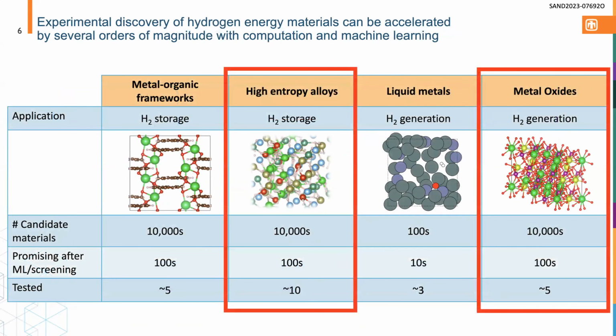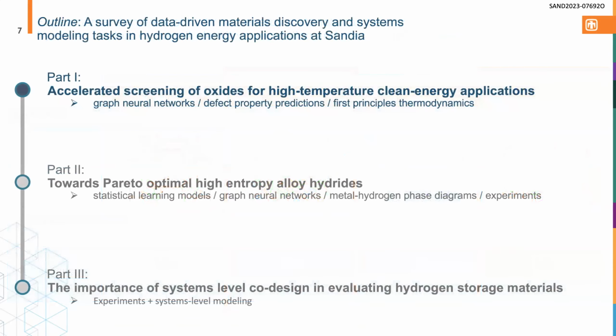So we look at a lot of materials at Sandia for hydrogen energy. Some of the things we touched on are metal organic frameworks, high entropy alloys, liquid metals, and metal oxides, kind of split between storage and generation there. The common theme is that there's tens of thousands of candidate materials, and we use machine learning to reduce the number of materials that are considered promising by several orders of magnitude, that basically shortlists things that you can then take over on chemical intuition to choose the final number of materials you actually want to test in the lab. And so we'll be talking about high entropy alloys and metal oxides today. So I'll go through three sections.